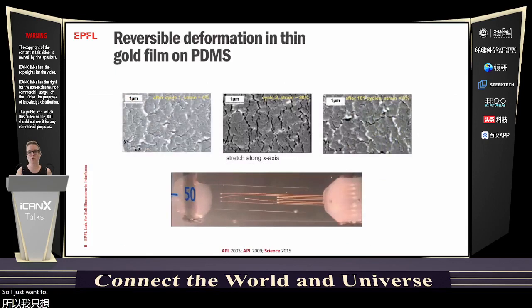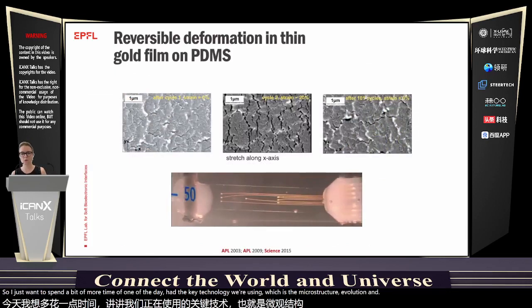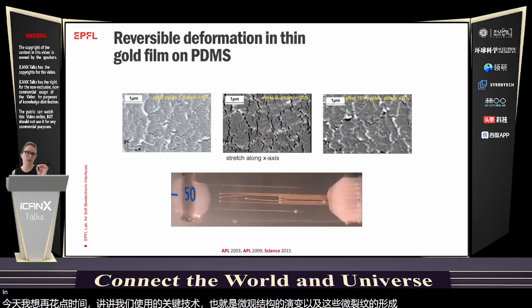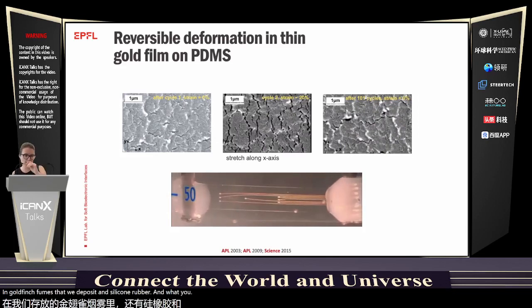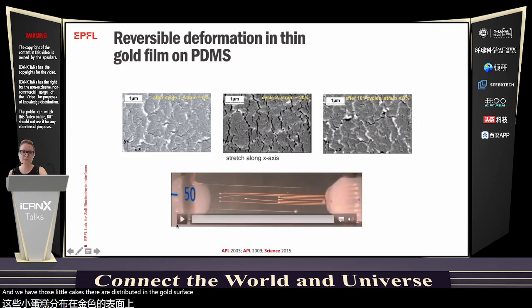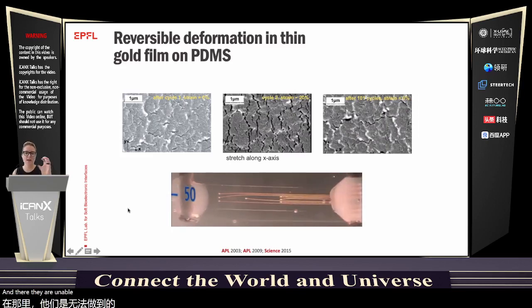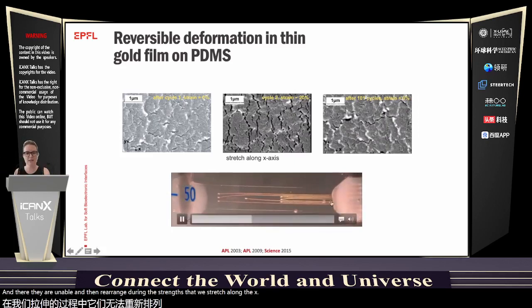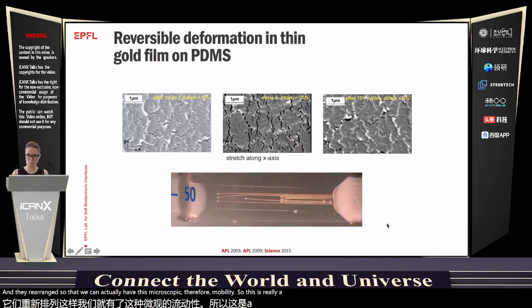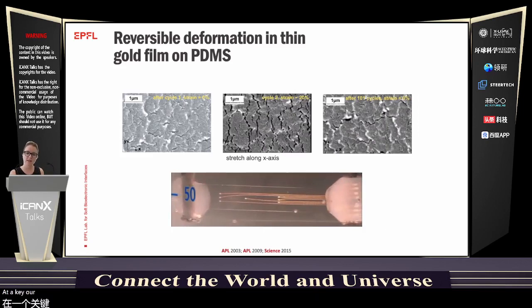I just want to spend a bit more time on one of the key technologies we're using, which is the microstructuration and the formation of microcracks in thin gold films that we deposit on silicone rubber. What you see here are SEM, scanning electron microscope, images taken of a gold film before stretching, during stretching, and after many cycles of stretching. We have those little cuts distributed in the gold surface, and they rearrange during the stretch. We stretch along the x-axis here, and they rearrange so that we can have this macroscopic deformability. So this is really a key structure design that enables the elasticity in gold films.